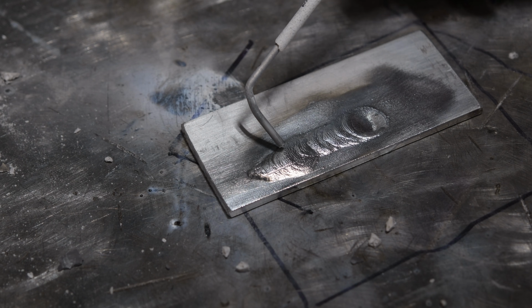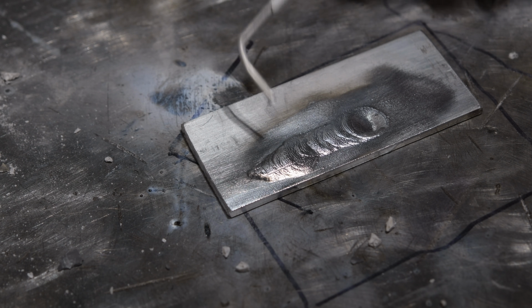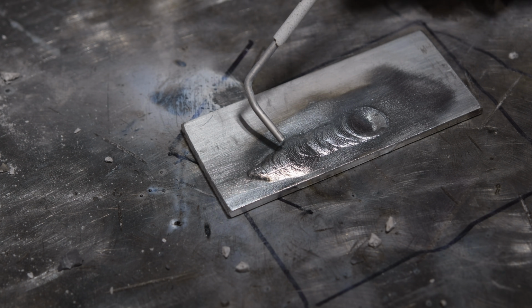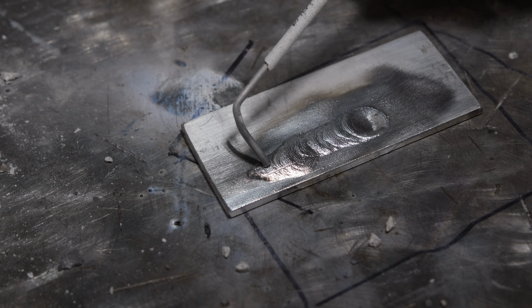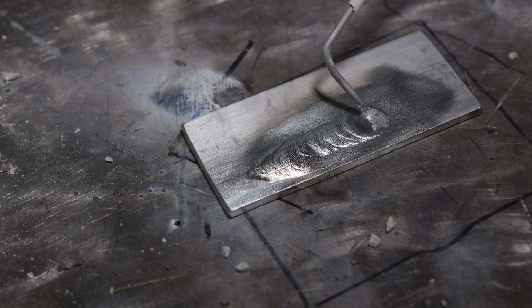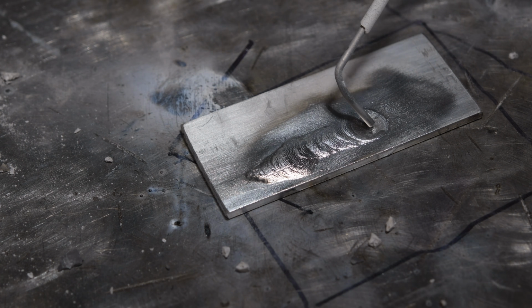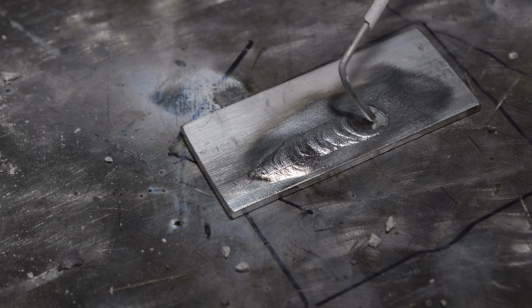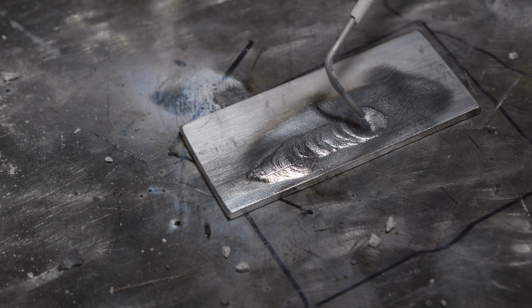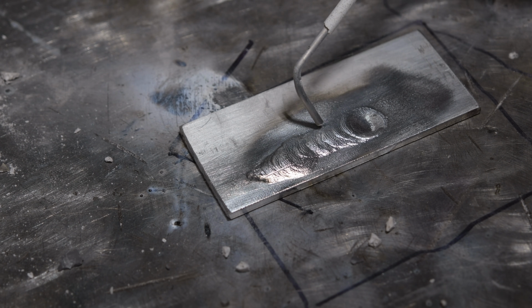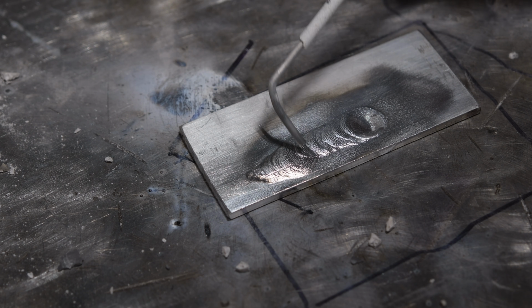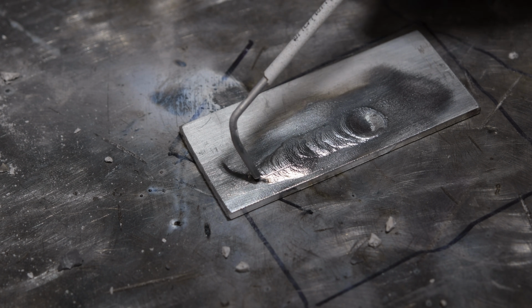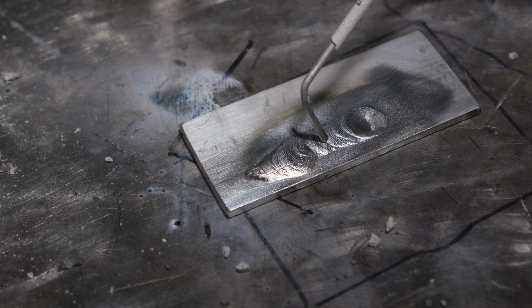Now, in the arc footage, you probably saw that it welded piss poor, to say the least. It welded terribly. You couldn't see what's going on, but the actual end results are far better. Now, there's a big enough crater here to stuff my house into, and that is probably going to cause a crack, or it's cracked already. You wouldn't want to leave that, but the actual weld bead looks far better wetted into the base material. It looks cleaner. I don't really see much of a defect other than the crappy start and the crater. The actual weld bead doesn't look that bad.